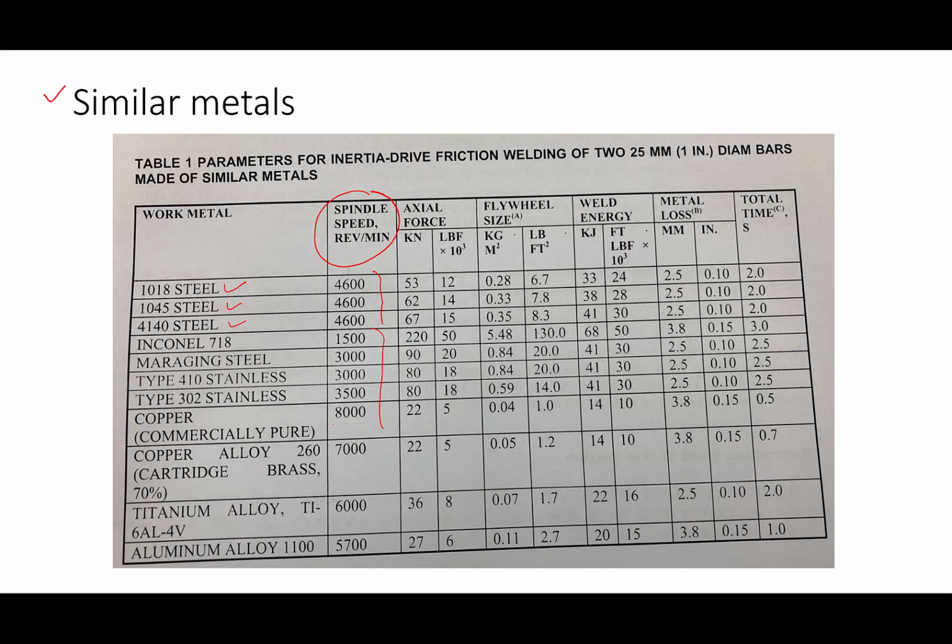To reduce the heat dissipation time for copper, a higher RPM is used. Pure copper is higher than copper alloys, which is a little lower. Considering their thermal conductivity or the temperature requirement, different RPM values are used, because a higher RPM generates heat at a much higher rate. It takes less time to reach the desired temperature.